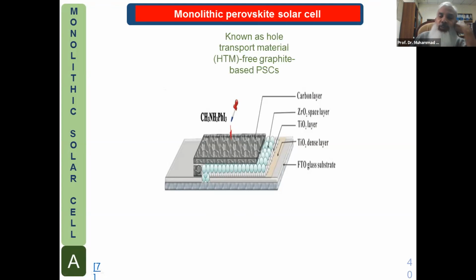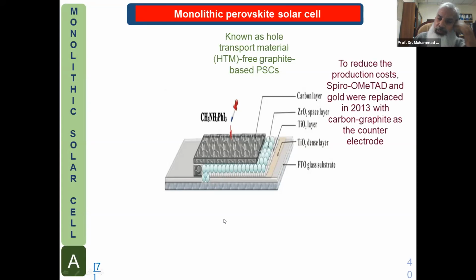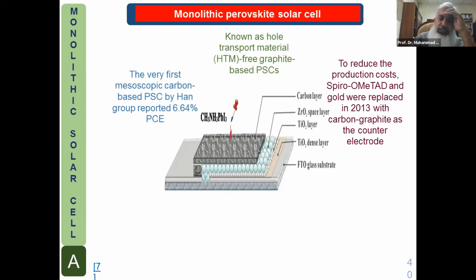This device is known as a hole transport material free carbon-based monolithic perovskite solar cell. And it is because in the earlier designs I have shown, spiro was used as a hole transport material, but that's expensive. And also they need deposition of gold and vacuum thermal evaporation is needed. So the technology is not scalable, but this is hole free and easy, and also it is scalable and printable. Every layer is printable. So it can be mass produced once its efficiency is enhanced reasonably, and its stability issue is resolved.